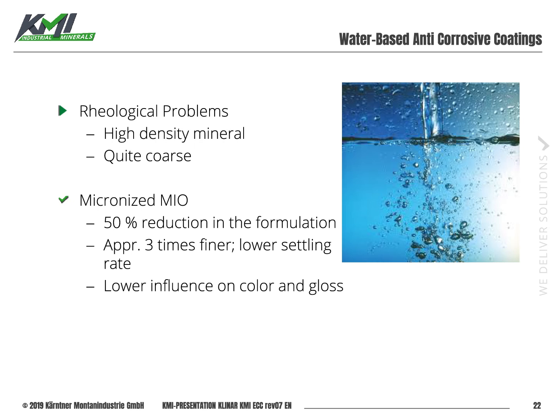The first new application is the usage of micaceous iron oxide products in water-based anti-corrosive coatings. If you want to formulate water-based and you want to work with standard grades, you immediately run into trouble because the product itself is quite coarse. You need a high loading level, and due to the high density, you always have rheological problems like settling rates and so on. With the micronized grades, you have two advantages. The first is the micronized grade is approximately 3 times finer than the standard grades, so that means you have a much lower settling rate. And the other advantage is you can reduce the necessary amount of MIO down to 50%. So it's much easier to stabilize. You have much more freedom in your formulation. And you have a lower influence on color and gloss.